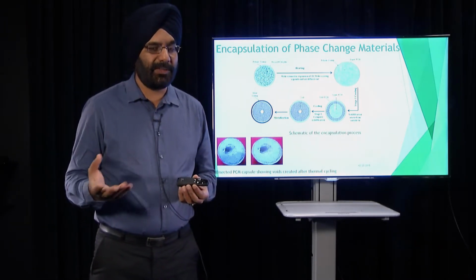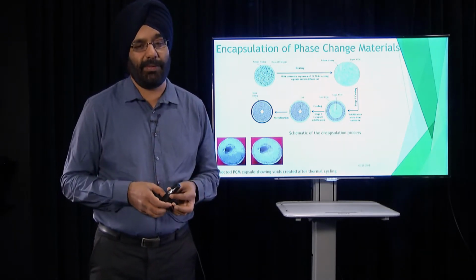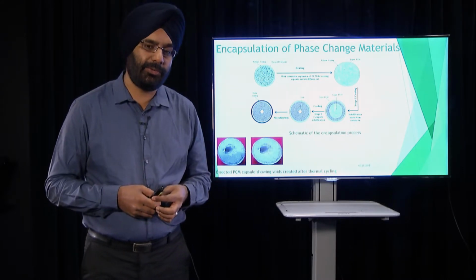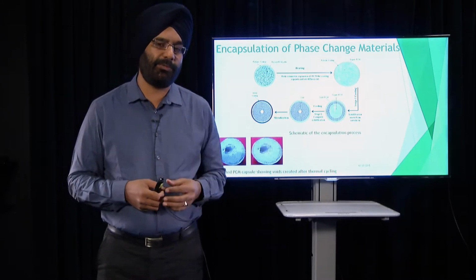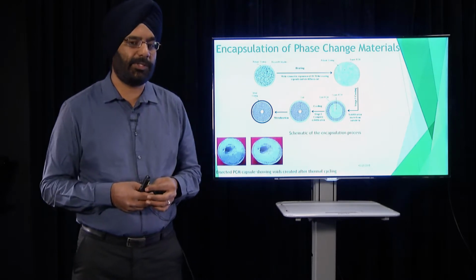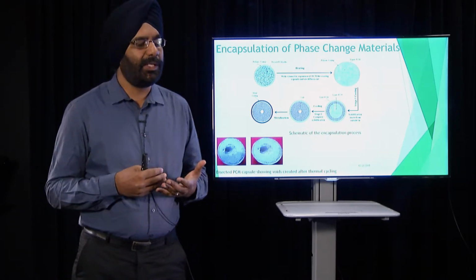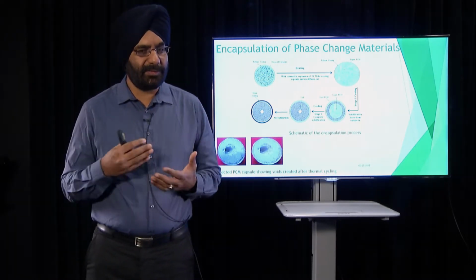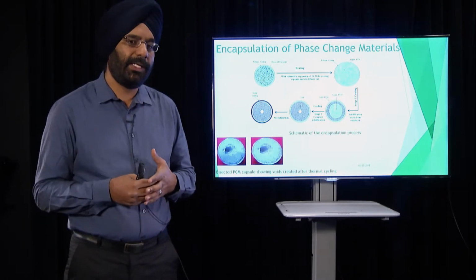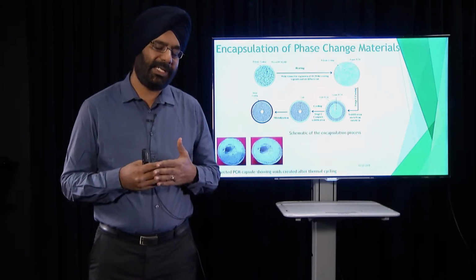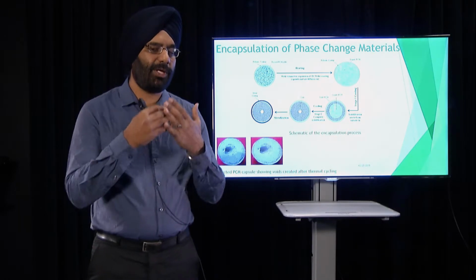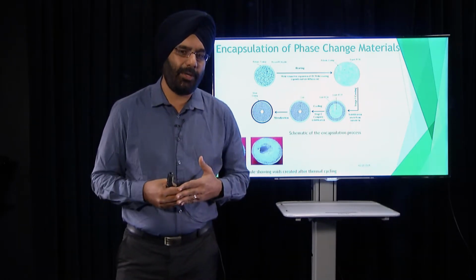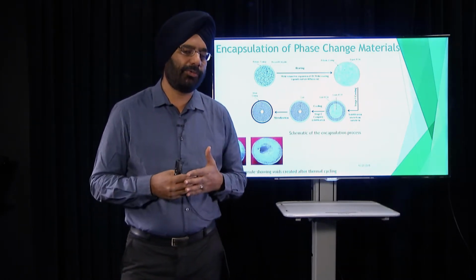According to one estimate, as I said, the pressure could be 25 times the original pressure, from 1 atmospheric pressure to 25 atmospheric pressure. So the idea here is to develop a coating which is selectively permeable. That means it allows the air to diffuse out, but it doesn't allow the molten salt to go out through those pores.